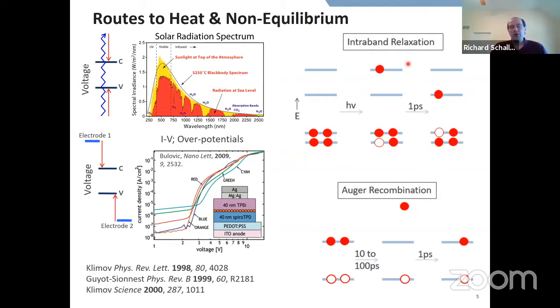In applications where you start to have more than one electron hole pair, and I'll focus a lot on materials that can show gain and lasing, you want to get things like population inversions. And so you have two electron hole pairs in this system here. These represent a population inversion, which is desirable, but they can also undergo this process that my former postdoc advisor, Klimov, found, where these become short-lived, 10 to 100 picoseconds, depending on the volume of the particle.